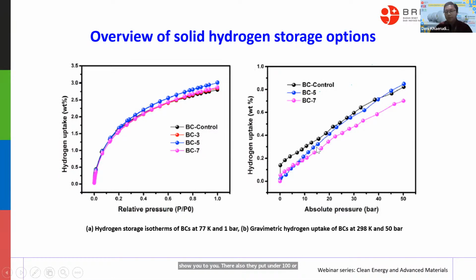Of course, this depends on our purpose. If possible, as I mentioned before, less than 30 bar, right? So the economics or the feasibility when we want to apply it at mass scale will be feasible. And again, you can see from the y-axis, the hydrogen uptake is low. Yes, and this is the challenge. Compared with this one, in vacuum or cryogenic conditions, it's easier to absorb, easier to store. But at room temperature, even though we put some pressure in here, the hydrogen uptake is not as high compared with the low temperature.